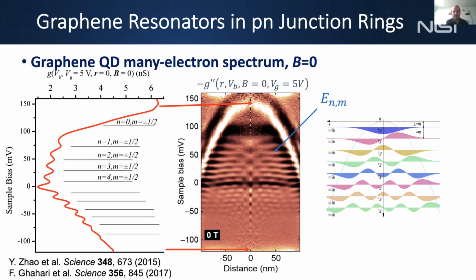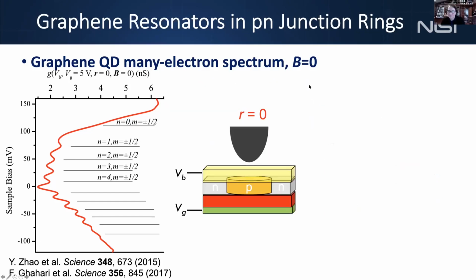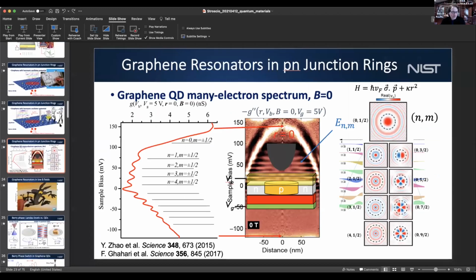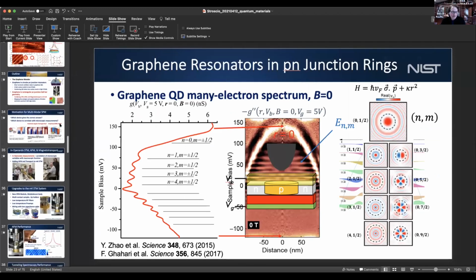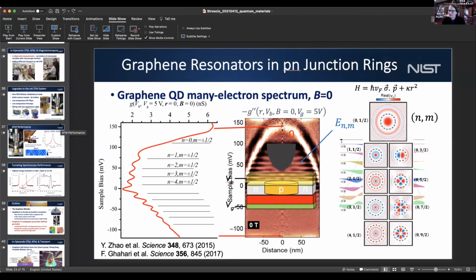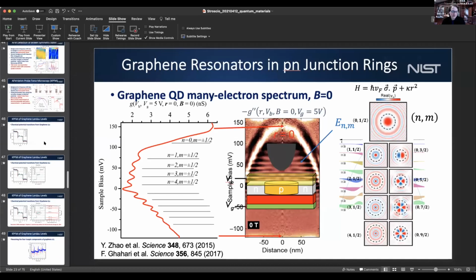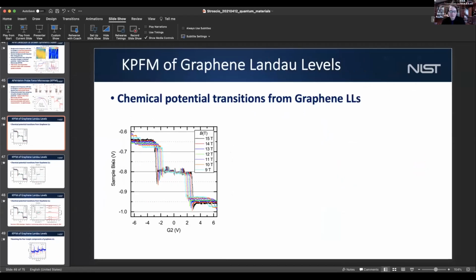Okay, thanks. I also have a few questions about the KPFM. The 1 millivolt resolution is really great. So what is your modulation voltage? We look at the AFM noise spectrum, and it has a lower noise level at low frequencies, so we're modulating the sample bias between 1 and 5 hertz. With which amplitude? Maybe like 20 millivolts, if I remember. Okay, tens of millivolts, and that's enough. I mean, it's very flat.